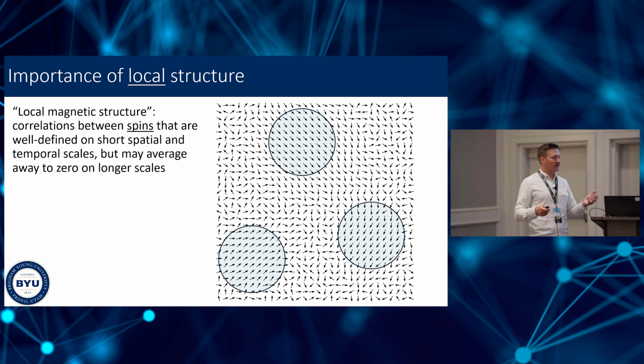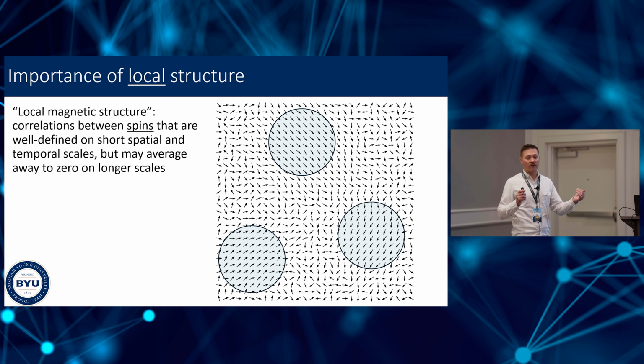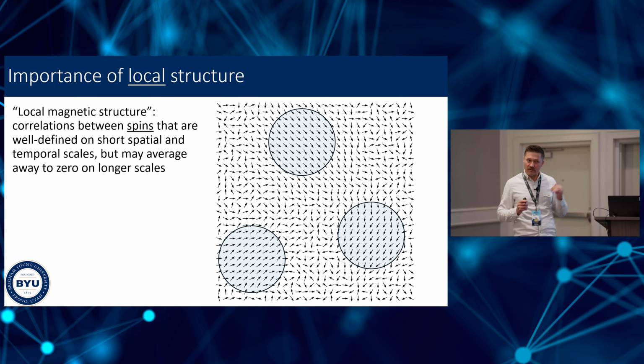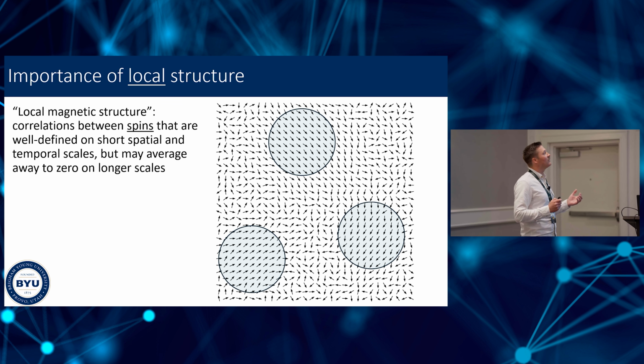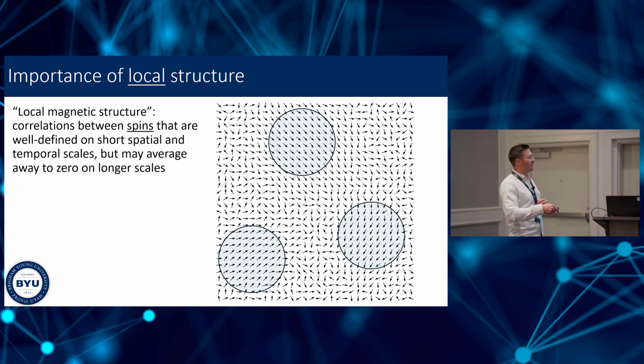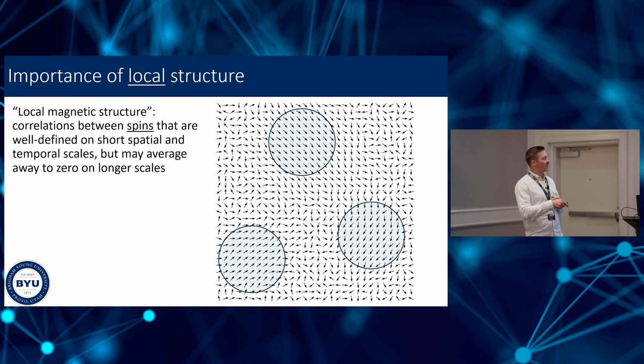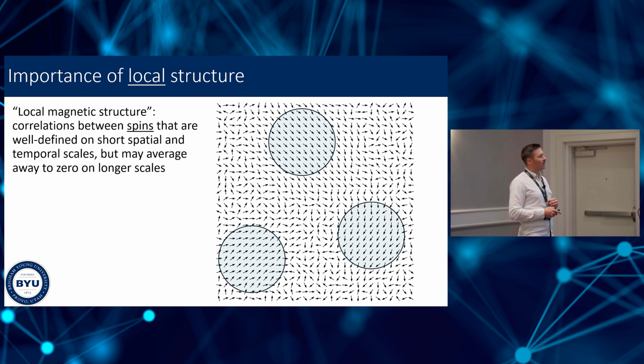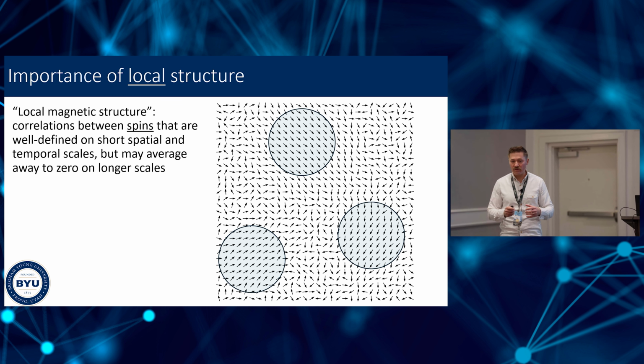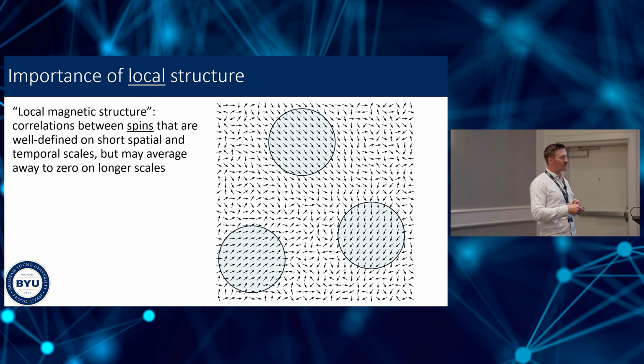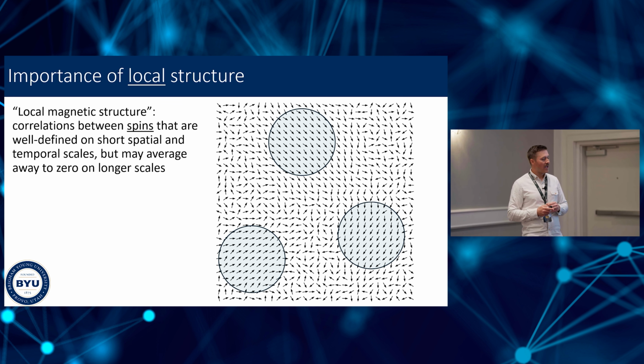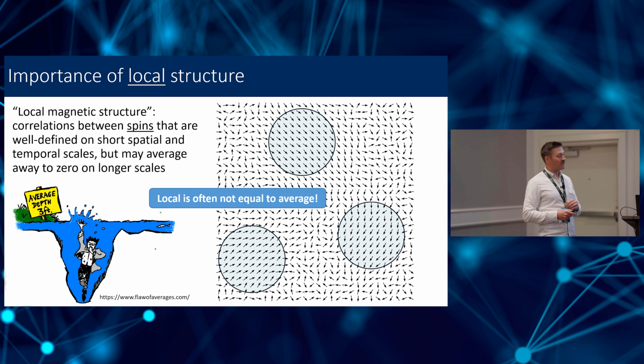A little more closely tied to what I'll be discussing later, how about local magnetic structure? Where now, instead of the correlations between atoms, we're talking about the correlations between neighboring spins, which again are non-zero, well-defined on local scales, but average away to zero on longer scales. For example, here we have some regions of ferromagnetically aligned spins. So if you look at any of these circled regions, then neighboring spins will have the same orientation or close to it. But if you go further away, it's essentially random. And these locally correlated regions are random with respect to each other as well. So on average, there is no long range, crystallographic magnetic structure here, but there's clearly some local spin correlations. All right. The point here is local is often not equal to average.